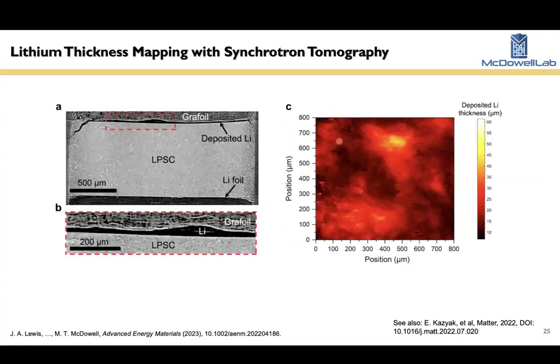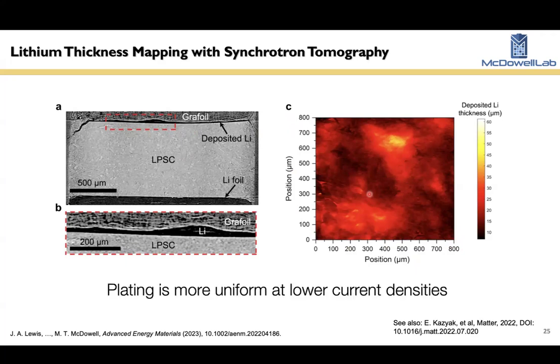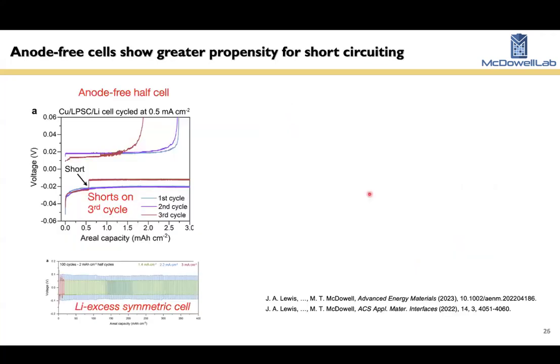That's a good start. We mapped out some of the details of this deposited lithium with synchrotron tomography. You can see generally when we deposit lithium, it's not that uniform. This is a height map of lithium metal across 800 by 800 microns of the interface. And you can see some regions are 60 microns thick, other regions are 15, 20 microns thick. So there is some variation in the thickness across the interface in these sorts of lab cells. And it's more uniform at lower current densities.